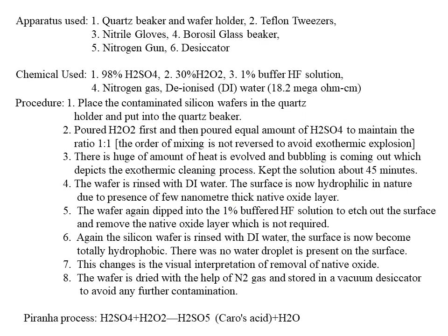So this is the final slide, the final process. In our piranha cleaning process, the main two ingredients are 98% sulfuric acid and 30% hydrogen peroxide solutions. But the acid cleaning process is very much exothermic, so we have to be very careful and take all precautions to run this chemical cleaning process.